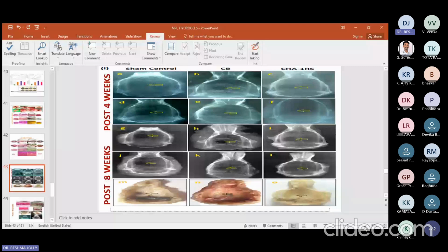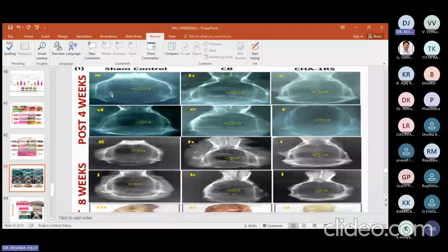These are after 4 weeks. Sham control means there is nothing, we have left it blank. This is that damaged part. And after 4 weeks, you can see the damage has not been filled. Obviously, naturally, a critical size defect cannot be filled. This is CB, Cerabone, the commercially available product. You can see after 4 weeks, it is available around the defect. The granules of the Cerabone can be seen.